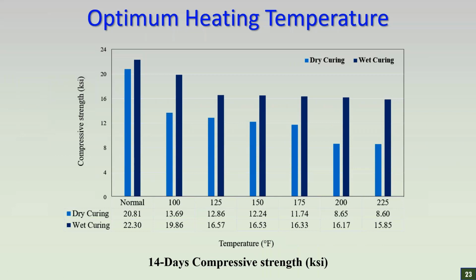When we heat the material, obviously it affects the properties of the UHPC. So compressive strength tests were performed on cubical specimens to see the difference in the compressive strength of heated ultra high performance concrete. Two different curing conditions, ambient and wet curing, were introduced for these specimens, which were heated from 100 Fahrenheit up to 225 Fahrenheit. It can be seen that under wet curing conditions, the reduction in the strength of ultra high performance concrete is very small. For specimens heated at 125 Fahrenheit, a compressive strength of more than 16 KSI can be achieved.